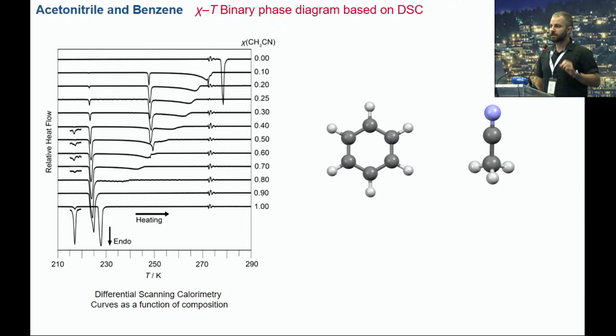Another big surprise: the phase diagram of acetonitrile is not known. It's the 21st century, and we don't know the phase diagram of a binary mixture that we all use. Sure, there are some descriptions from the 1930s, but back then, the DSC didn't even exist. So we decided to go back and recreate this phase diagram based on differential scanning calorimetry, a very suitable method to do so. We can look at the crystallization, and we can look at the melting.